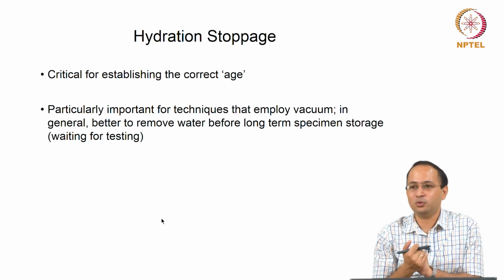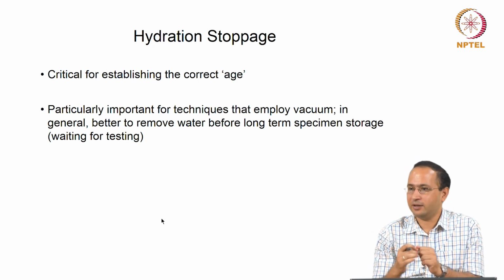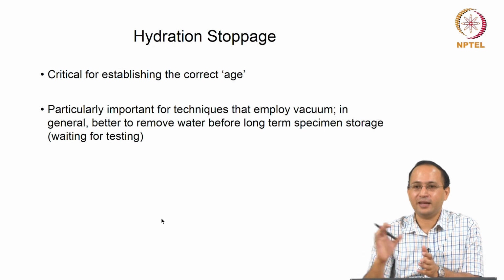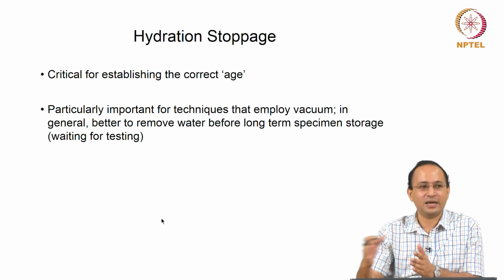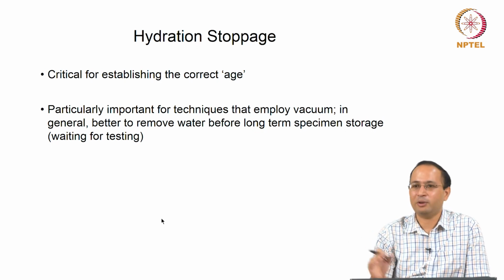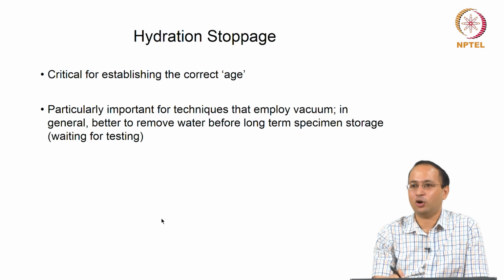What we usually do is we collect the sample, we grind it, we stop the hydration and then store it for some time. Then we can do analysis depending on availability of instrument. That is the usual way, right. Not all the time can you do a test immediately after. Suppose you want to test it after 7 days, you go to the field after 7 days, but you can't carry out all the techniques on the same day, ideally. So what we do usually, we collect the sample, then treat it, stop the hydration and store it. Then depending on the availability, we do the test, right.